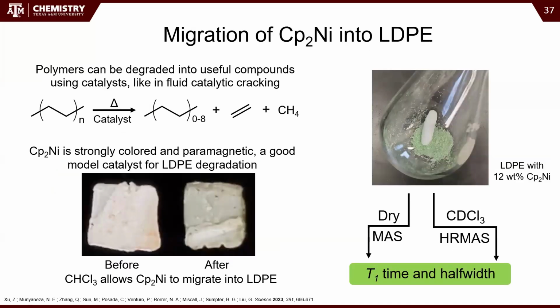We also wanted to see if that solvent penetrating into the polymer network can bring in a small molecule. So we used Cp2Ni (nickelocene) as an example. So Cp2Ni (nickelocene) is a catalyst. We could theoretically use that for polymer degradation. It's also strongly colored and paramagnetic. So we can visually see that it's penetrating all the way in 3 millimeters through this pellet. And we can also see because it's paramagnetic, it won't overlap in the NMR.